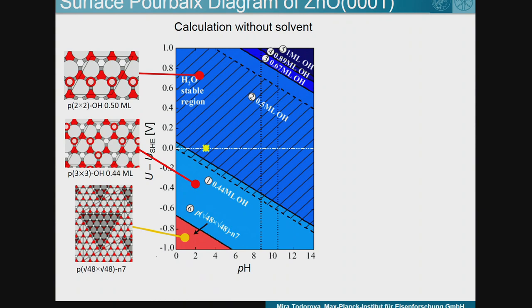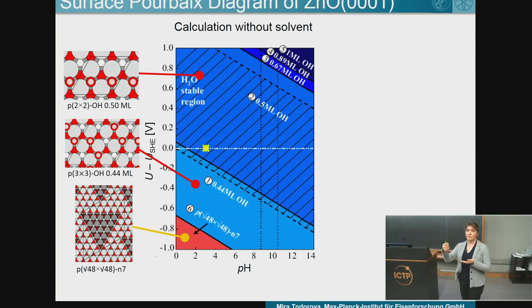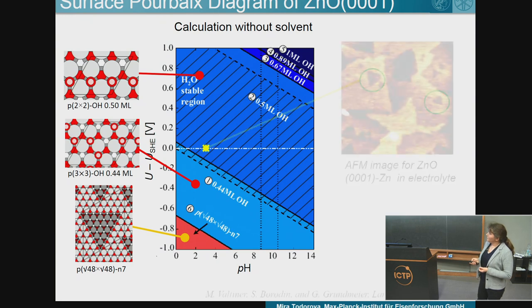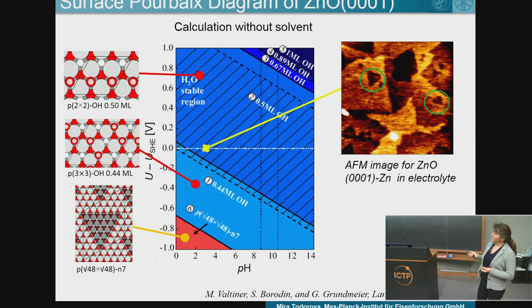We built now such a Pourbaix diagram once for the calculations without the solvent. You don't have to understand all the details, just what I would like you to remember is that these blue phases are as-cleaved surfaces with various coverages of OH group on the surface, while this red surface is a triangular reconstruction. We do have one experiment which is at these conditions, and when we compare, we see that they do have triangular reconstructions here. So obviously, we are not quite describing reality here.